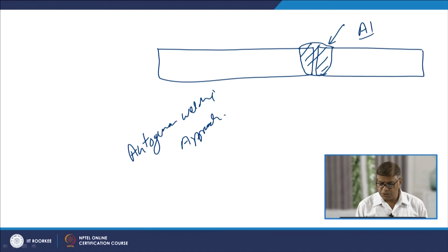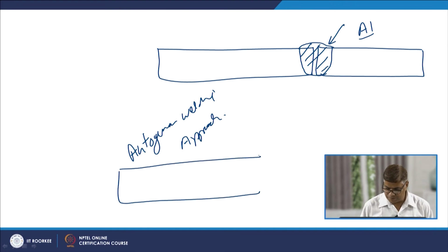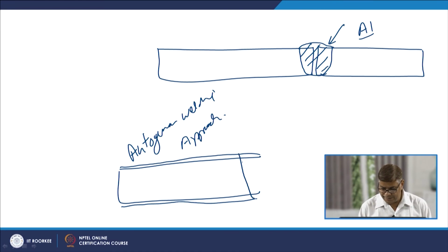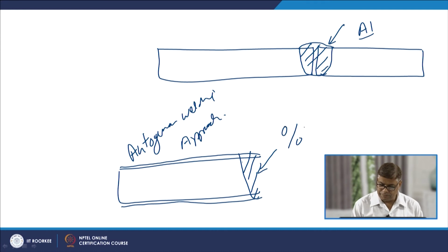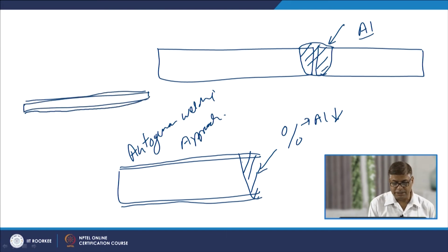Now, we need to see one very simple thing. When the thickness of the sheet is more, the aluminum coating of a particular thickness is being used, and when we melt its portion, the aluminum will be going into the weld metal. But when we use a thick sheet, the percentage of aluminum in the weld metal is low as compared to the case when an aluminum coated thin sheet is welded. The proportion of the aluminum going into the weld metal is much more.